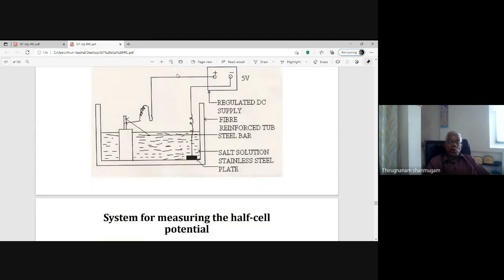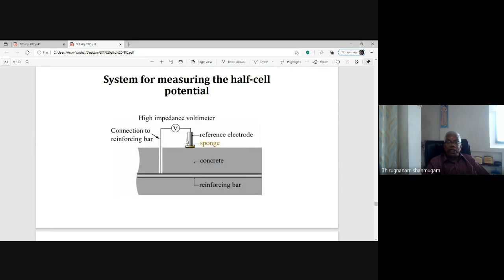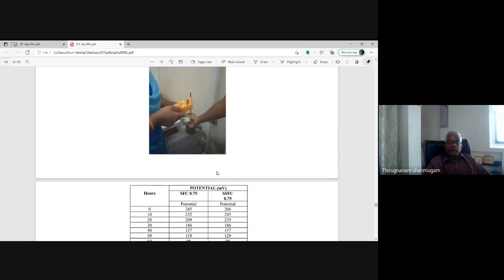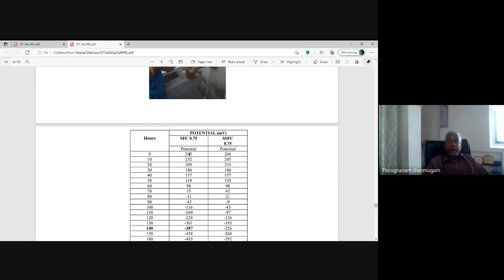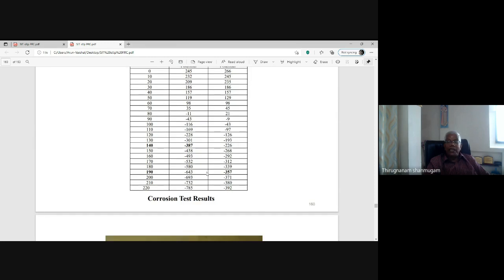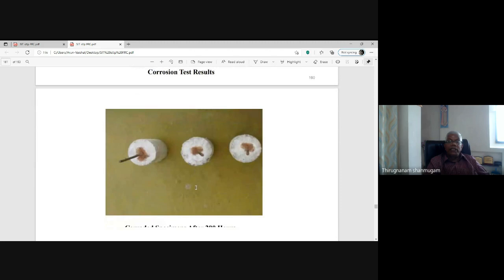And these beams are subjected to an accelerated corrosion test setup, and this is the schematic diagram. And this is a half cell potentiometer for measuring the corrosion level. These potentials are tabulated like this. For the steel fiber reinforced concrete, 245 initial reading, and near about the same, 266. But at a later stage, at 140 hours, it exceeds the corrosion limit of minus 350 millivolts. Whereas here it is within the limit, minus 226, and it takes more time, 190 hours, to reach the minus 350 demarcation point. At this point it involves severe corrosion of these fibers. So at the end, this one is maintaining the same thing. The propagation is not taking place at all, but here the propagation leads to failure of the structure, at 200 hours. This is the view of the specimens after corrosion.